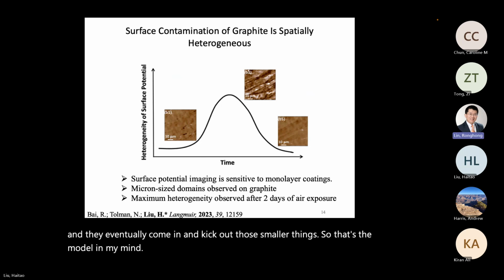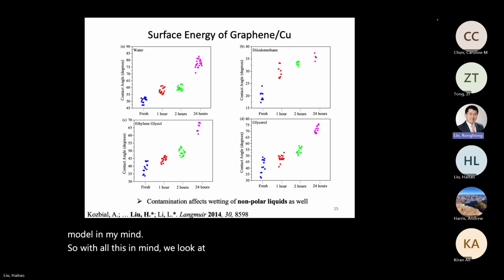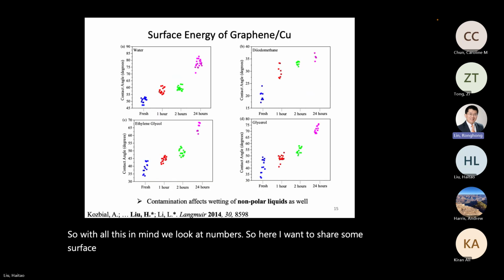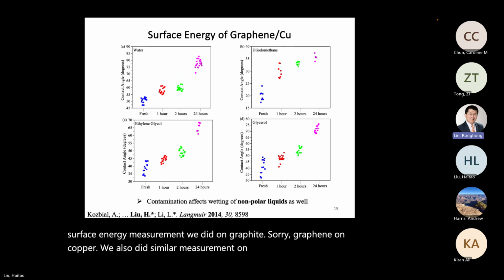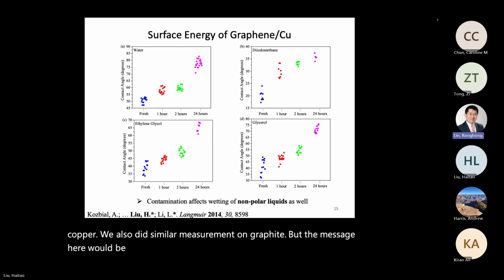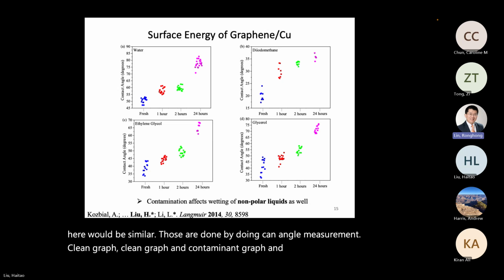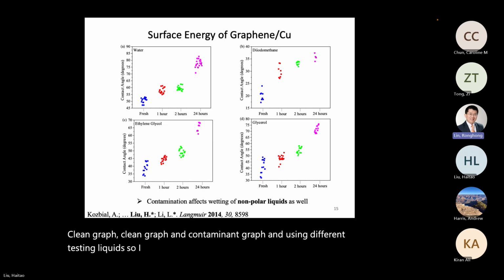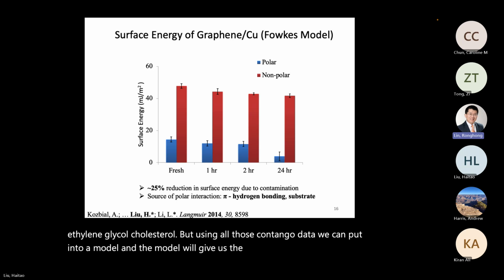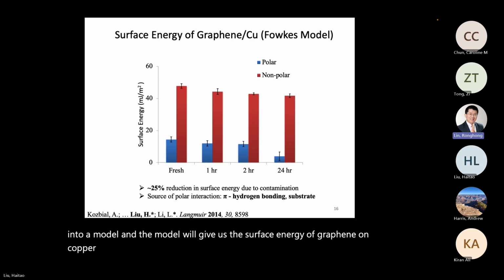So with all this in mind, we look at numbers. So here I want to share some surface energy measurements we did on graphite, sorry, graphene on copper. We also did similar measurements on graphite, but the message here would be similar. Those are done by doing contact angle measurements on clean graphene and contaminated graphene using different testing liquids. So I showed data using water. We also did diiodomethane and ethylene glycol, glycerol. But using all this contact angle data, we can put it into a model, and the model will give us the surface energy of graphene on copper. And that is the data here.